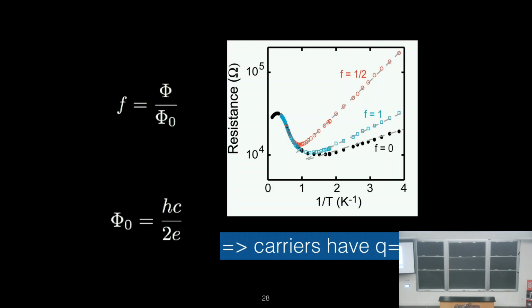So what Stu found was that he measured the resistance as a function of 1 over temperature, and it rose kind of exponentially here. He turned on a magnetic field corresponding to 1/2 of a flux quantum per unit cell, and it went high. He went to 1 flux quantum, it went back down. And the period is set by the charge, which sets the flux quantum. The period said that the carriers have Q equal to 2e. So the charged carriers were 2 electrons at a time.